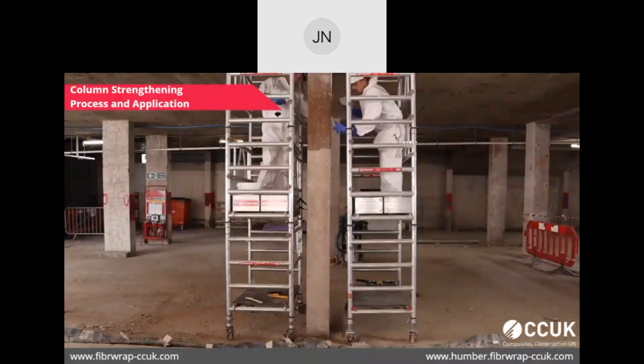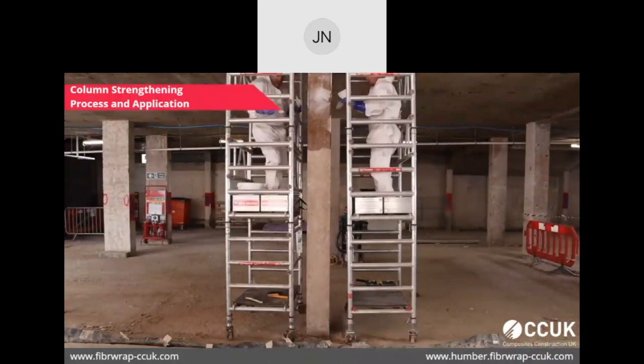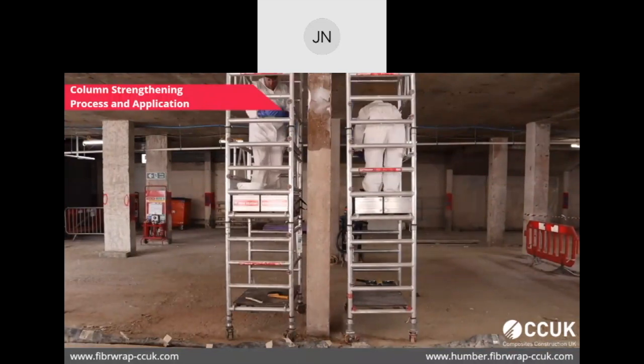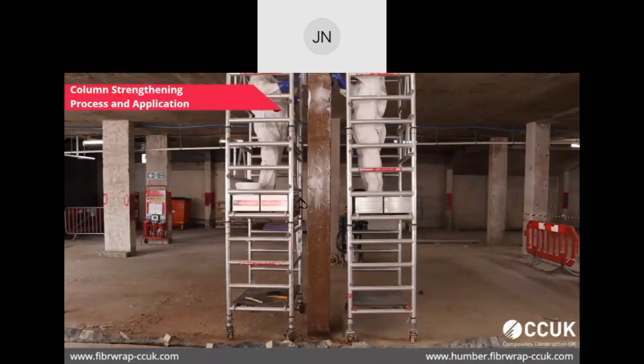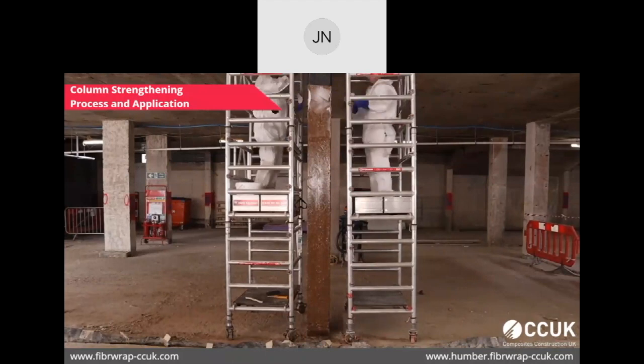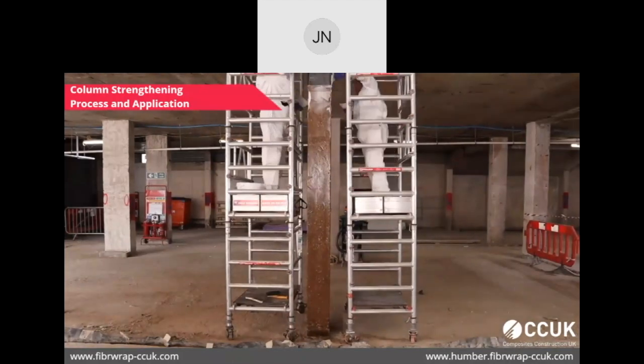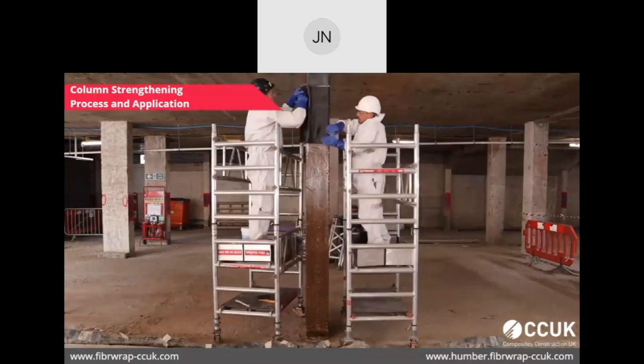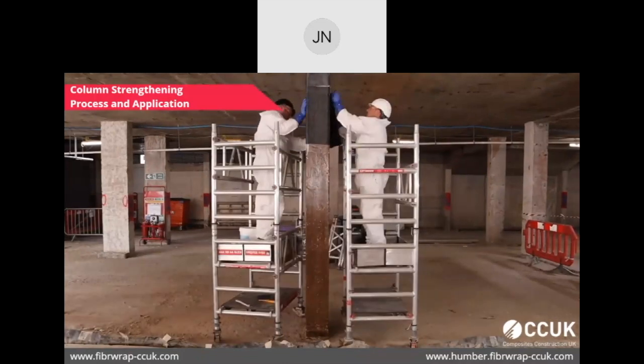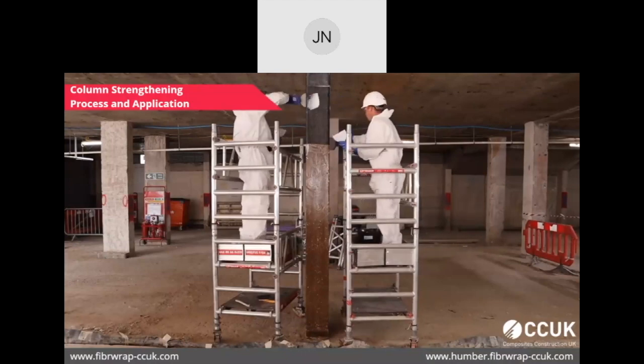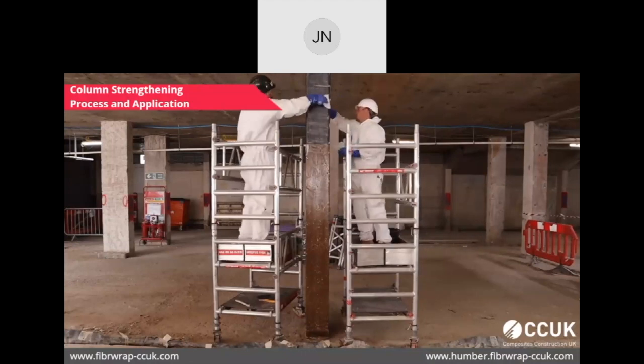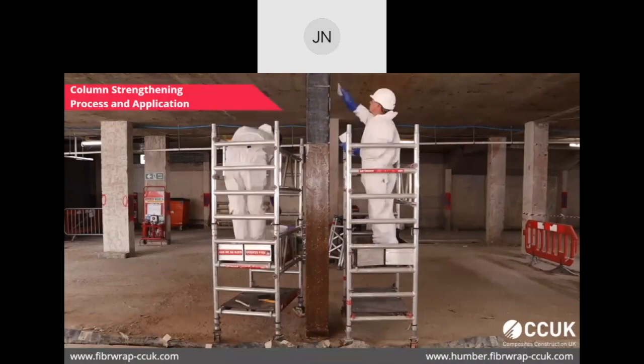The first application process will be priming, then application of thickened epoxy, and that will be followed by the pre-saturated fibers. Because it's a strengthening for axial load, the FRP will be applied in the hoop direction. So once you apply the first coat of thickened epoxy, you apply the first layer of carbon fiber, and again press it against the concrete column. So squeeze out all the excess epoxy, then put another layer, and that's how you keep on applying until you get the ultimate number of layers as per the design.